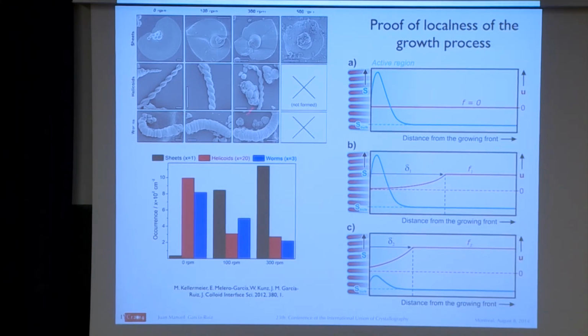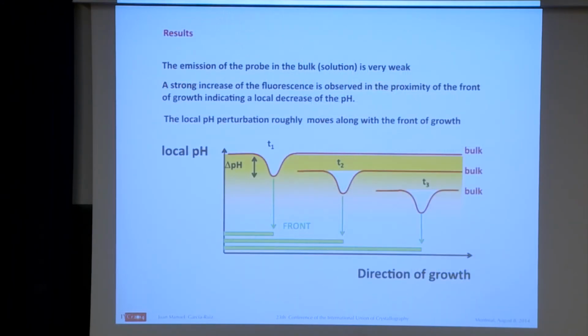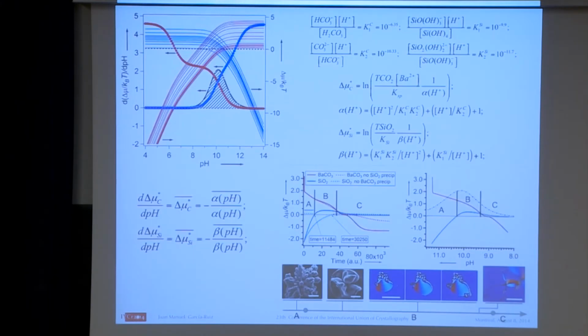Why we say that is because you can perform this experiment with 300 revolutions per minute of stirring, and still you have the formation of these shapes, okay? And remember, these are self-assembled nanocrystals. So everything depends on the kind of physical forces that induce the nanocrystals to self-co-orient one each other, okay? So we think that what really is interesting is what happens in the internal, no, in the growth front, okay?